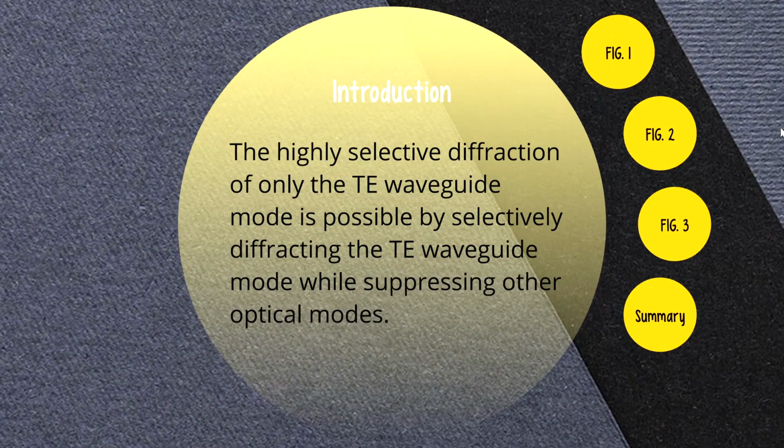Diffractive optical elements have also been used to extract thin-film optical modes for directional emission, and subsequently emitted photons are coupled into a thin-film waveguide strip and extracted by the DOE pixel, yielding directional emission. However, the device efficiency is very low. Here, we demonstrate highly polarized light emission from OLEDs on a grating substrate to selectively extract the TE waveguide mode by suppressing the SPP, TM waveguide, and air modes.